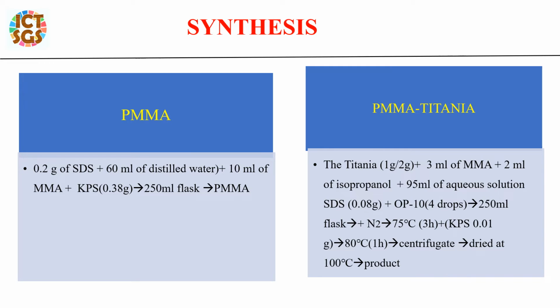The resulting milky dispersion was purified with centrifugation-redispersion cycles several times until no free polymer exists. Each time the supernatant liquid was removed and then replaced with deionized water. The product was dried at 100 degrees Celsius. For Titania 2, the same procedure was followed.